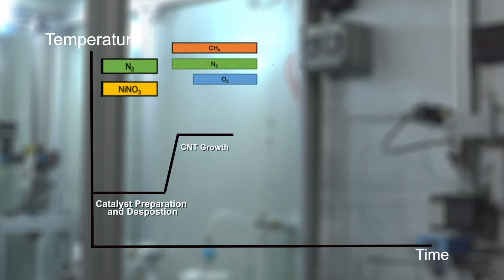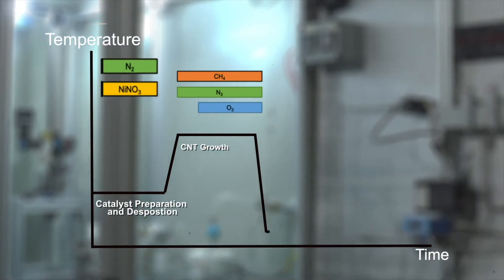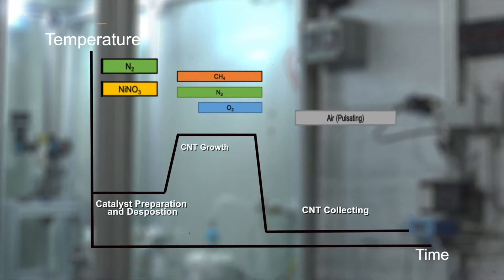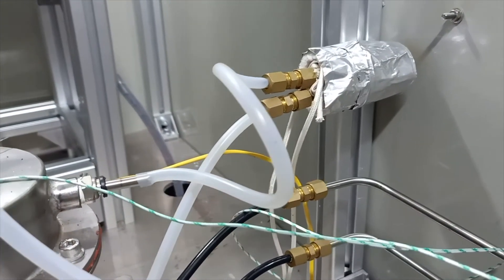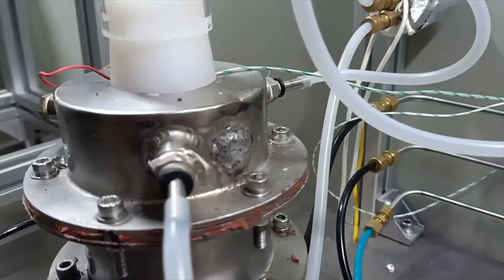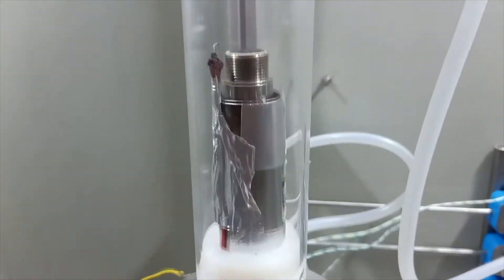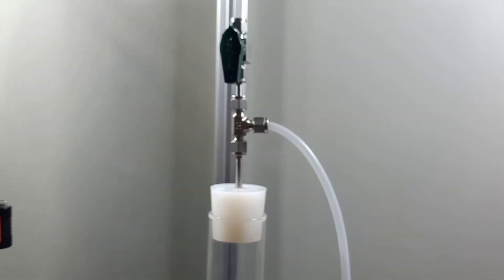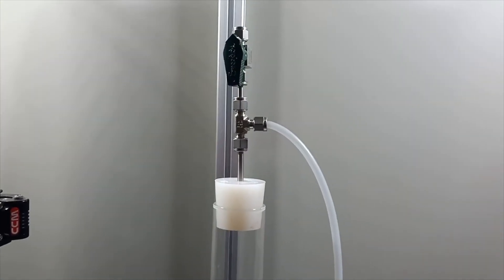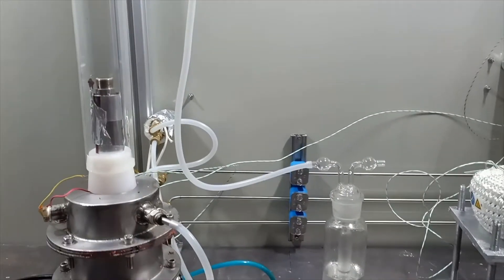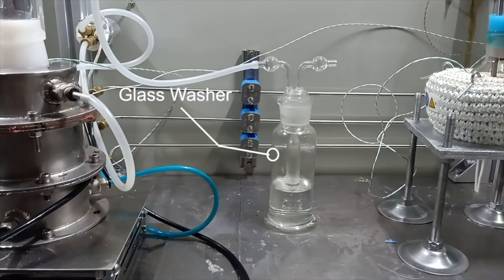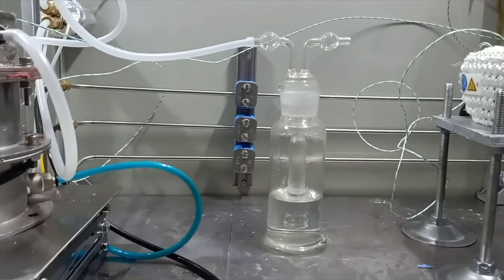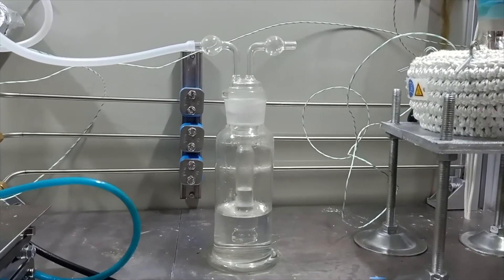Once ready, the coated ceramic beads are exposed to a flat flame for a certain period of time and the carbon nanotubes are collected within minutes. The flame is contained within a synthesis chamber in the form of a quartz tube to ensure well-controlled gas composition within the synthesis region. Using a high-equivalence ratio flame, additional carbon from combustion is used as the carbon source. To ensure safe exhaust gas, a glass washer is utilized at the outlet of the quartz tube to trap any nickel vapour carryover.